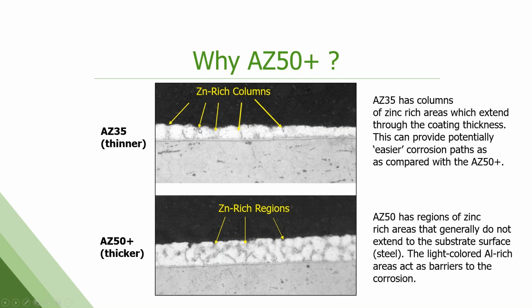So on these thinner coatings, like we just talked about, the zinc sacrifices itself. It's going to go first. So what happens on these lower coating weights that have the zinc areas that go all the way to the base steel, once they've exhausted themselves and are done, you now have an open pathway to the base steel through the aluminum. But on the higher coating weights, you're much less likely to have that because there's so much more aluminum left at the surface.